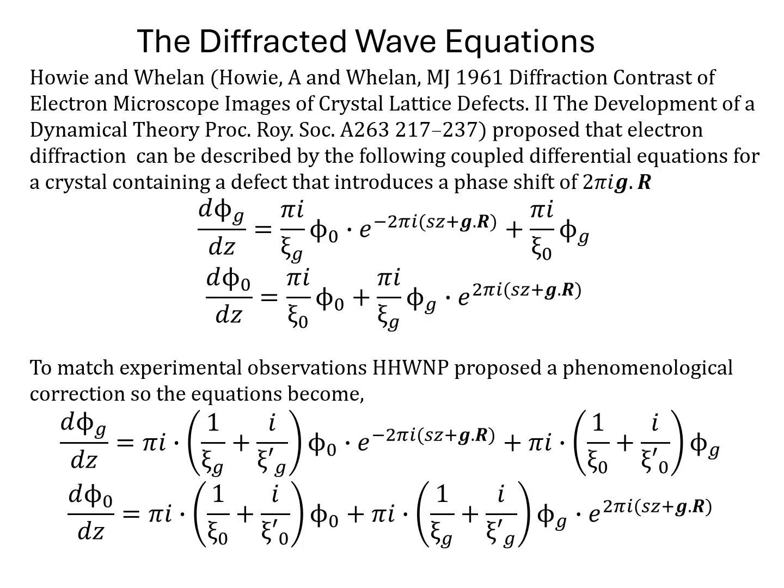In an electron microscope, with electron diffraction in a material, it's a lot different because the electrons interact so strongly with the crystal that when they're diffracted, they can all then rediffract and interfere with the direct beam.